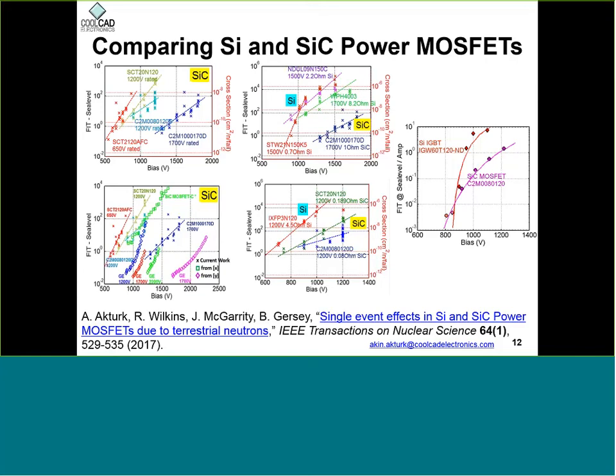So at high biases, especially closer to the rated voltage, silicon almost always fails at a higher rate. But as you go down in bias for the same type of device, there tends to be a crossover point below which silicon carbide fails at a slightly higher level. But at that point, the failure rate is generally very low. So depending on the application, this may be okay, or the part needs to be derated.